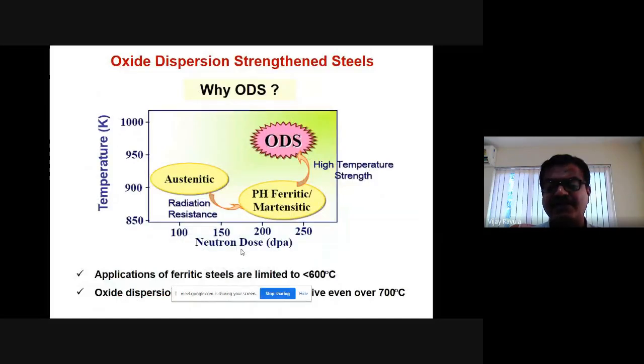And why oxide dispersion? Look at the temperature and the neutron dose. Conventional austenitic steels have high active elements and also get void swelling. Ferritic martensitic steels can take higher dosage, but the operating temperature is lower. But when we put in oxide dispersion, they act as sinks for the neutrons and don't allow knocking out of the elements in the material. So it can take higher neutron dose as well as higher temperatures.